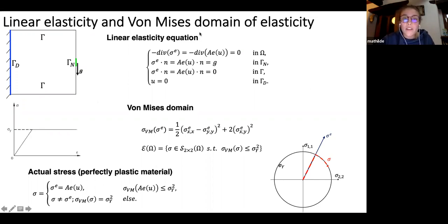And we want to optimize under a von Mises constraint, so we don't want any plasticity. How to characterize this? Well, basically the actual stress within the solid will be the ideal elastic stress whenever this stress satisfies this von Mises condition. And it will be a stress satisfying this equality when this ideal elastic stress is getting too strong. So intuitively, if we're in a good basis for the stresses, when the ideal elastic stress remains in the circle, then we don't have plastification. But as soon as this ideal elastic stress is out of the circle, the actual stress has to follow the boundary of the circle here. And this means that we have plastification, which we want to avoid.